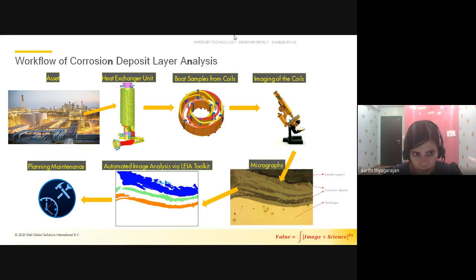Now, in this Pearl GTL plant, coils in the syngas effluent cooler, SEC coil in short, undergo severe corrosion as I explained. Now, out of a total 36, two of them we know have been inspected via these microscopy images. And what you see in the right and bottom of this slide is a SEM image of the sample that contains bands of different colors, yellow to varying shades of gray, and finally black, right? From bottom to the top of the image.